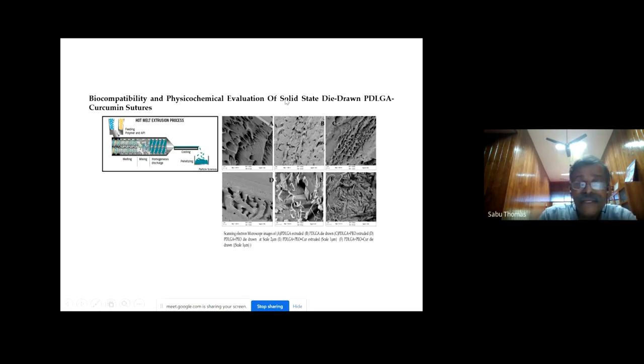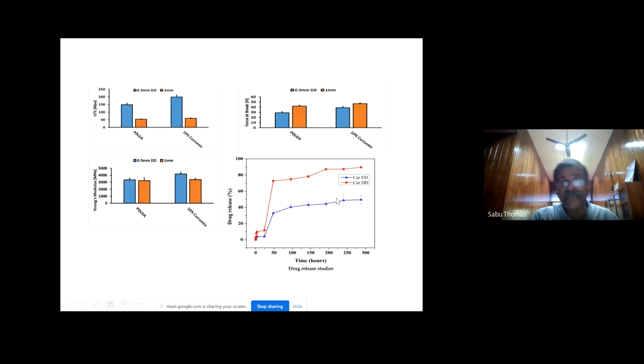See, this is the neat PLA fiber. We call it PDLGA. It's a copolymer of glycolic acid and PLA. This is after drawing. You see the difference after drawing. During drawing, you can orient it. This is actually PDLGA and PEO combination before drawing, after drawing. The last one is PDLGA, PEO, and curcumin. You can see these are the curcumin. The square things are curcumin. And after drawing, you see a lot of orientation taking place. Let me show you another very interesting slide about the mechanical properties. We have made two different types of fibers. One is 0.5 mm diameter and one is 1 mm diameter.